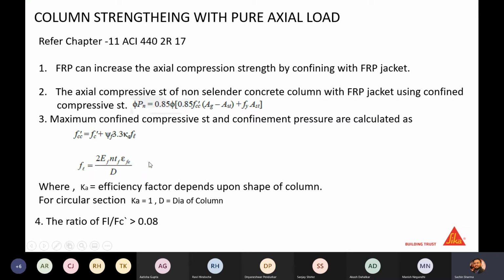the column, FL is the confinement pressure, and FCC dash is the maximum confined compressive strength. So what we have done is we have increased the compressive strength of the column from FC dash to FCC dash by creating the additional confinement pressure. And this is the ratio that you need to check. This FL by FC dash should be greater than or equal to 0.08. So this is the method as per the ACI.